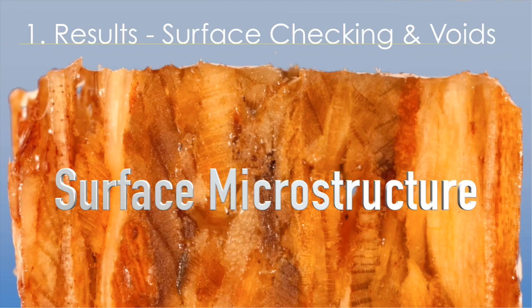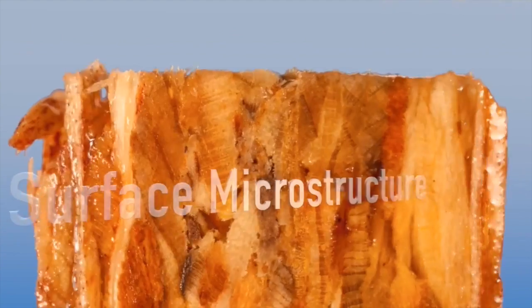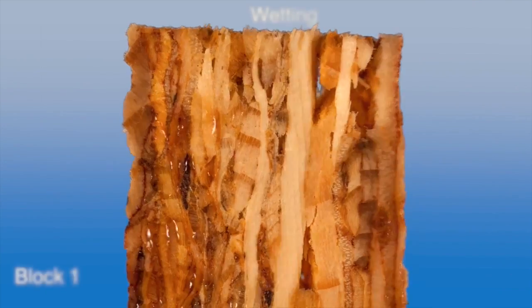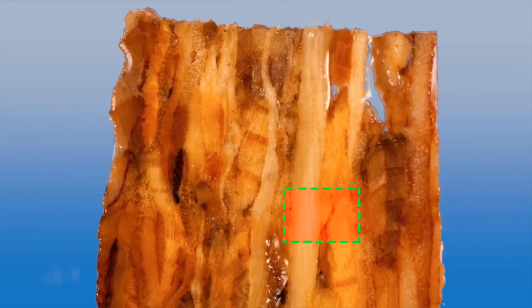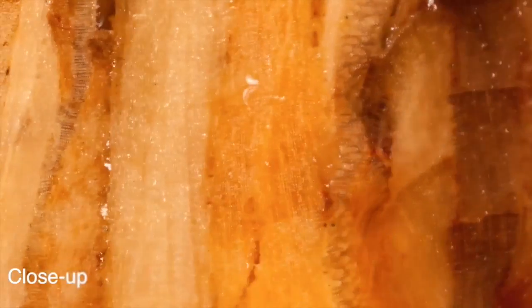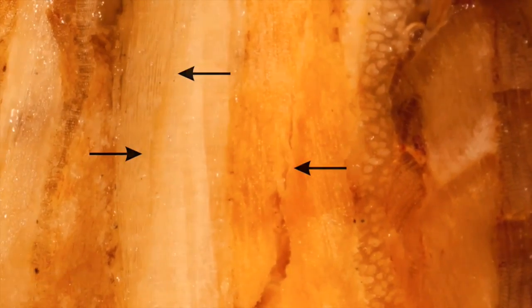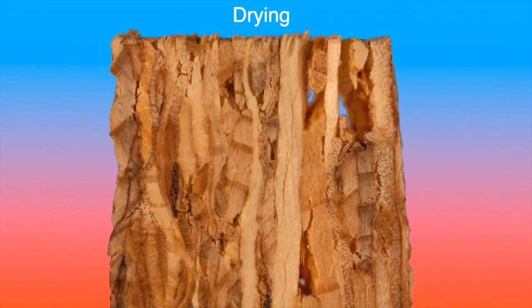So now I'd like to show you the results of this study. I'd like to start by showing the results on the surface checking obtained by the macrophotography. So as you can see from this animation, which is a time-lapse from swelling and shrinkage, it shows checking developing during wetting and partially closing during drying.